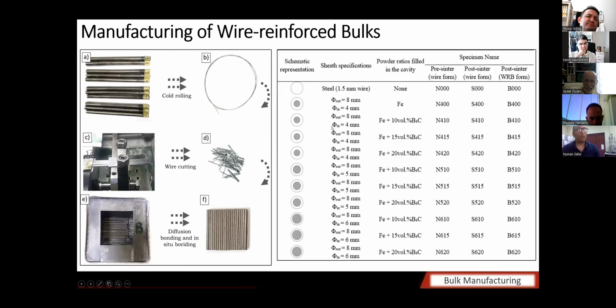These are the types of wires I have produced for the second generation, for the bulk material. Because I have seen that the iron boride phases can be synthesized in this way, I expanded the study. So I compared this with the reference material, a steel 1.5 millimeter wire, no core, no reinforcement, nothing. So it is a zero specimen. Then there is a core with only iron particles. Then there is a core with 10, 15, and 20 volume percent reinforcement ratios.